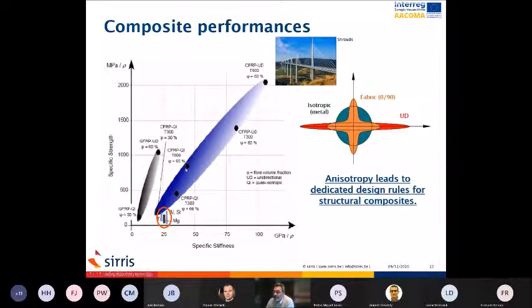If you use T300 fiber, you come from this point to this one. And now, if you do not use a specific high-performance process which allows 60% of fiber in your product, but only 30%, you are here. And you see that you become less performant in terms of stiffness, and you are still with carbon fiber, but you remain very interesting in strength. So now you understand why it's very interesting and very complex to design a composite product that is better than a metallic structure, even if you use the best products. The carbon fibers, the T800 or the T300, are very performant structures, but you have to take into account all the parameters to be sure that you design your product with the same or better performance than the metallic.